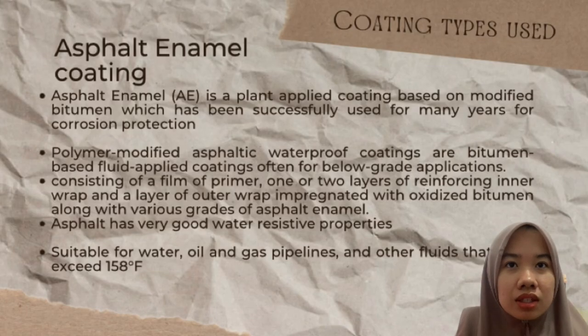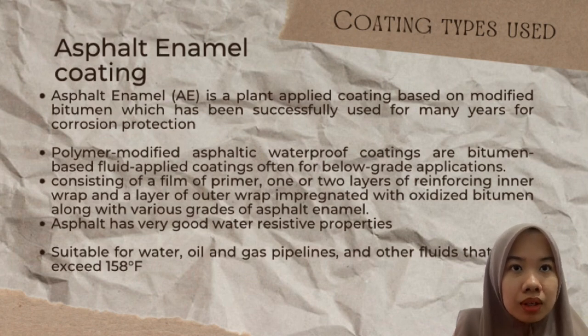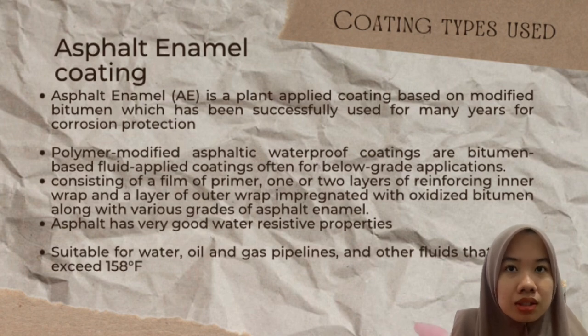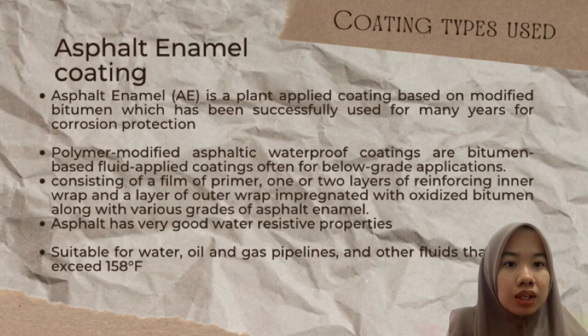The coating type that we choose is asphalt enamel. It is a plant-applied coating based on modified bitumen which has been successfully used for many years for corrosion protection. It is a polymer-modified asphaltic waterproof coating, a bitumen-based fluid-applied coating often used for below-grade applications. It consists of a film of primer, one or two layers of reinforcing inner wrap, and a layer of outer wrap impregnated with oxidized bitumen, along with various grades of asphalt enamel. Asphalt has very good water-resistive properties, and it's suitable for water, oil and gas pipelines, and other fluids that don't exceed 158 degrees Fahrenheit.